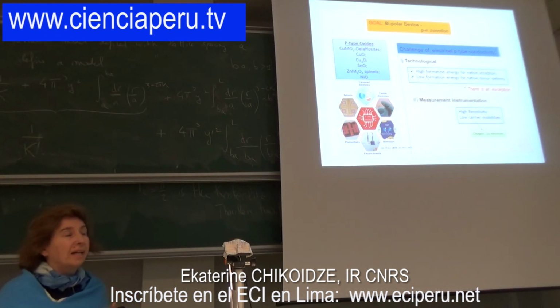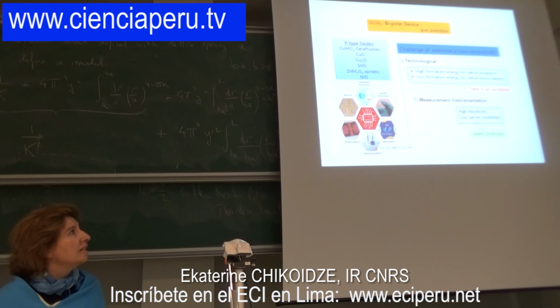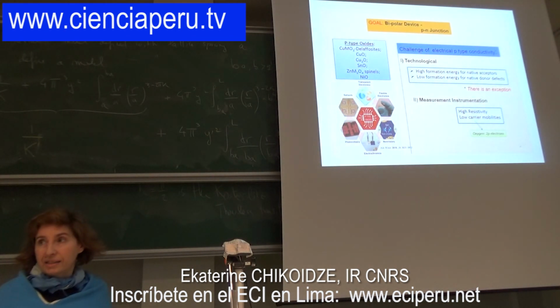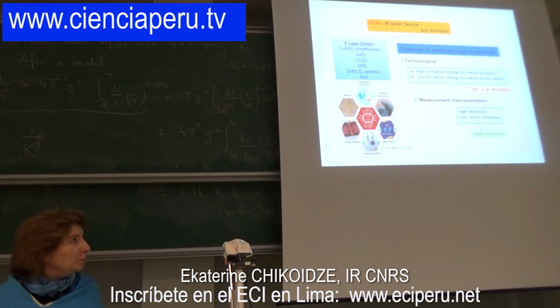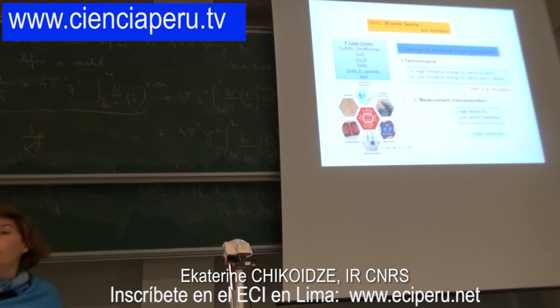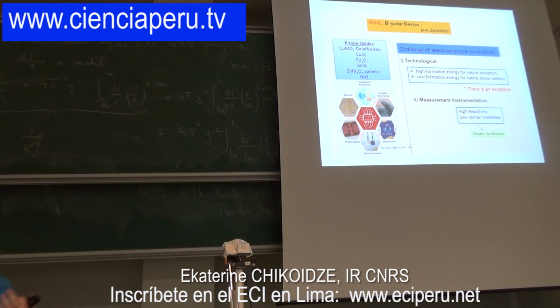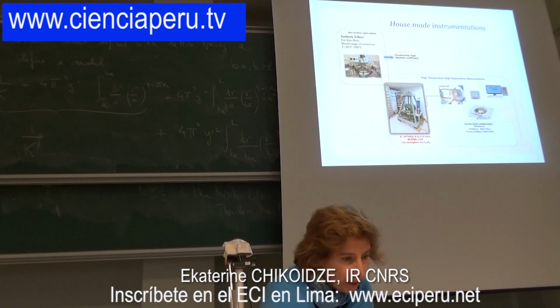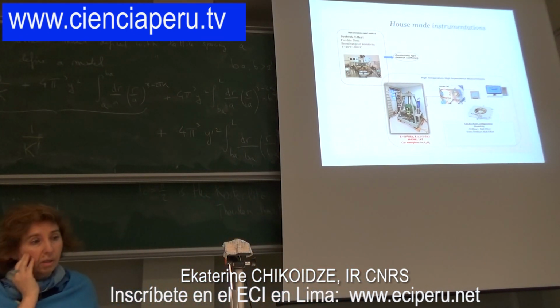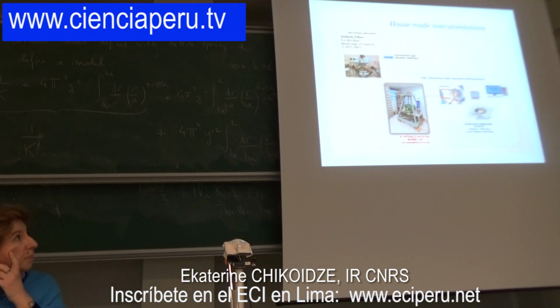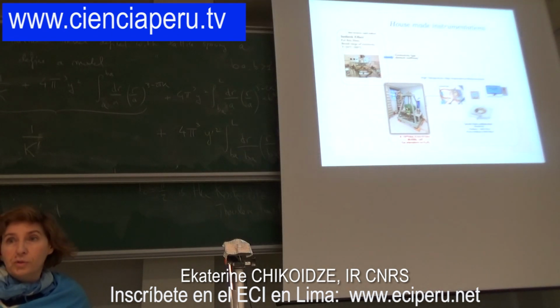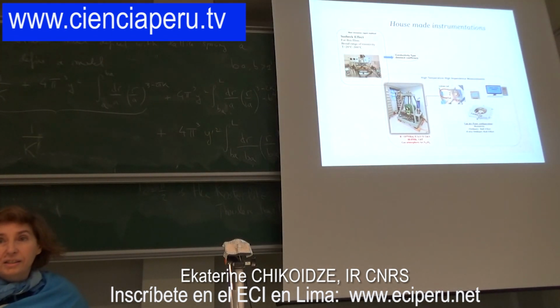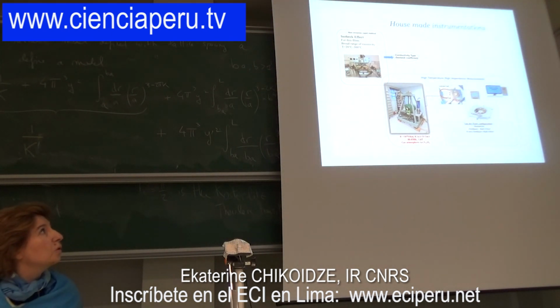Why, in fact, by measurement technique, what makes it difficult is that materials which are p-type are usually highly resistive, and their carrier mobility is very low. So when we are doing the Hall effect, which is primus inter pares to show the general type of conductivity, it's very difficult to extract Hall voltage from these materials. So that was the reason that in GEMaC, where we have been specialists for many years in wide bandgap materials, we developed special instrumentation dedicated to measuring highly resistive materials and also materials with low mobility.